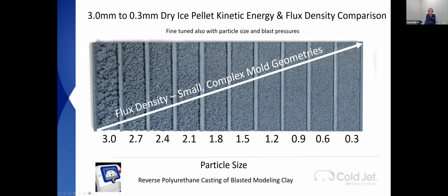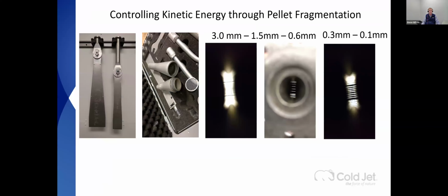So when you need to get into tight, small geometry, small places, you're better off going down to the smaller particles. On the other hand, when you need more kinetic energy, you get more kinetic energy as you go up. When you go to clean a screw, you're going to use the 3 millimeter side or something in between there. So there's advantages inside of a molding shop. There's times you want to go 0.3, 3.0, or somewhere in between, and then save that recipe.